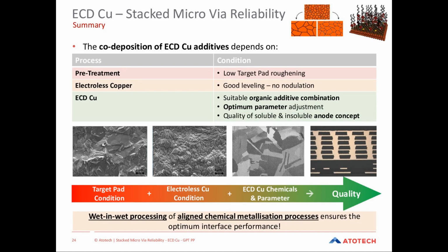And of course, the electroplating copper process itself. Here, you need the right combination of additives. Of course, it is not only selecting the right additives, you also need to find the right balance of the additives, so that none of these additives is dominating the absorption on the target pad. And there are also other parameters you see in the following table, which also can be adjusted to avoid excessive absorption of organic additives on interfaces. And what we also found by our studies is that in general, systems with insoluble anodes have less absorption on interfaces.